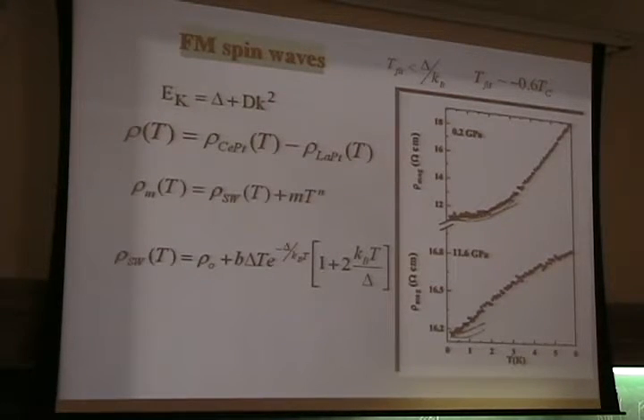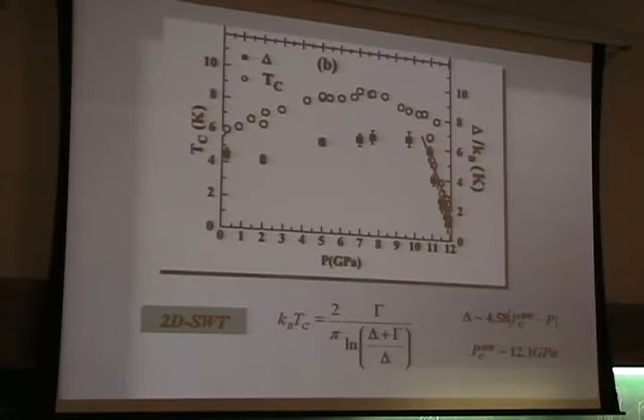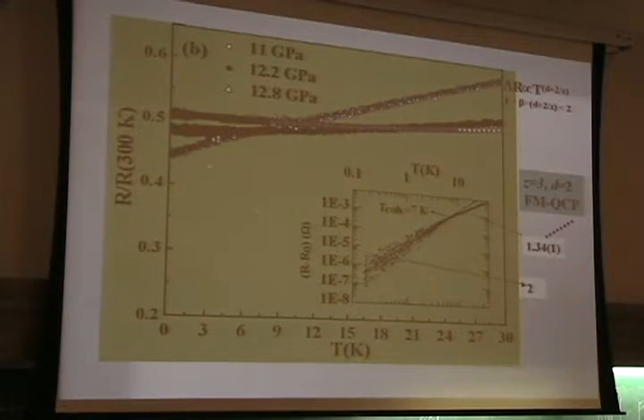D is the stiffness for these spin wave materials, and you see that the gap follows a power law that could be well fitted with this law. This is actually linear. Okay, with the difference between the Pc and the pressure, okay, and this could give us a critical pressure that is around 12 gigapascal, and it's in agreement with this behavior. You see, from linear behavior to some square behavior after this pressure here.